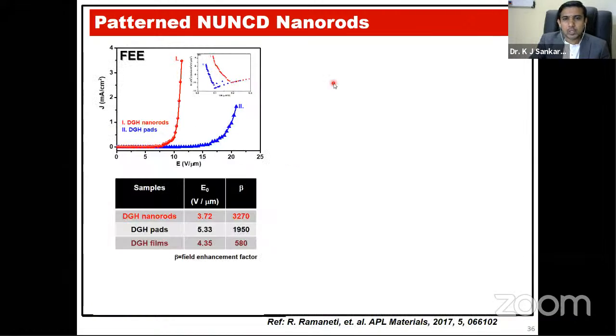So how is the electron emission compared between the DGH pads and DGH films? These NUNCD nanorods show a very low turn-on field and a very good field enhancement factor. The field enhancement factor increases, which increases the emission current, and the low turn-on field results from this high aspect ratio.